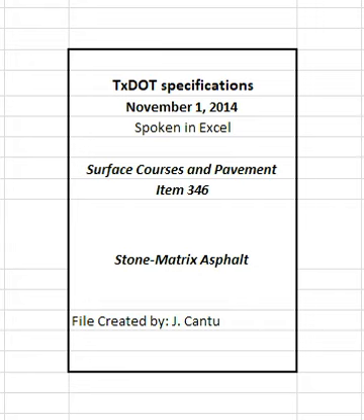The engineer will take immediate possession of the untrimmed cores and submit them to the construction division, where they will be trimmed if necessary and tested for bulk-specific gravity within 10 working days of receipt. The average bulk-specific gravity of the cores will be divided by the engineer's average maximum theoretical specific gravity for that lot to determine the new payment adjustment factor of the sublot in question. If the new payment adjustment factor is 0.700 or greater, the new payment adjustment factor will apply to that sublot. If the new payment adjustment factor is less than 0.700, no payment will be made for the sublot.